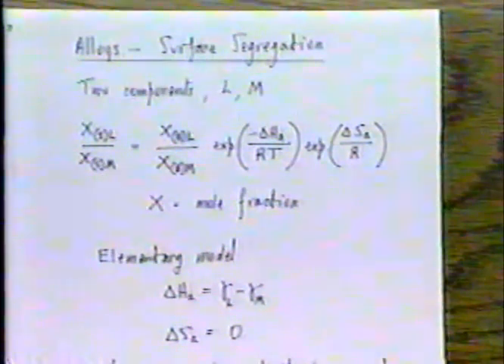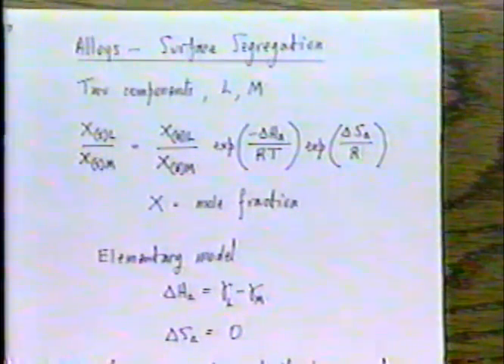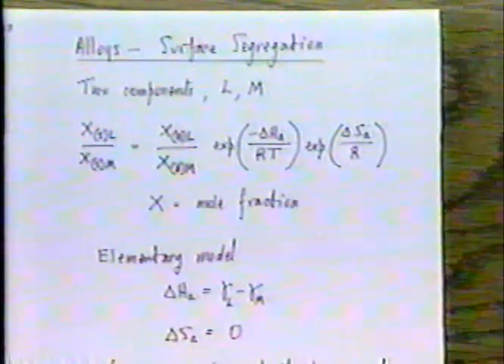And it will not be so because the two components, L and M, taken separately, are almost certainly going to have different surface energies. And so if you make an alloy of these two components, the total free energy of the system can be minimized if the component with the lower surface energy accumulates in the surface. That is to say, there will be a migration of the component with the lower surface energy from the bulk, which is depleted thereby, to the surface, which is thereby enriched.